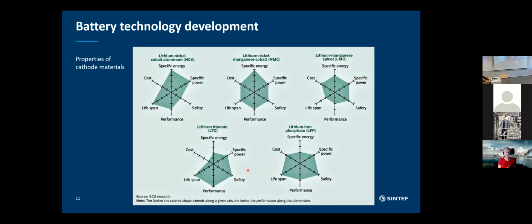But then, some of you may have heard talk about different battery chemistries. When we say different battery chemistries in relation to lithium ion batteries, we're talking about different cathode chemistries using different cathode materials. Here we also often use a lot of short terms. So for instance, NCA, that's short for lithium nickel cobalt aluminium oxide. NMC, or NCM, as some prefer to say, is lithium nickel manganese cobalt oxide. Then there's the LMO, which is lithium manganese spinel oxide. And another material which is becoming more and more relevant is LFP, which is lithium iron phosphate.